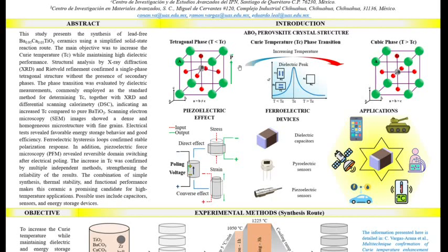As temperature rises, the dielectric constant climbs and peaks right at the Curie temperature. That's the ferroelectric to paraelectric transition. Push past that temperature, and the structure snaps into a cubic phase. Titanium moves back to the center, the dipole disappears, and the material becomes paraelectric.